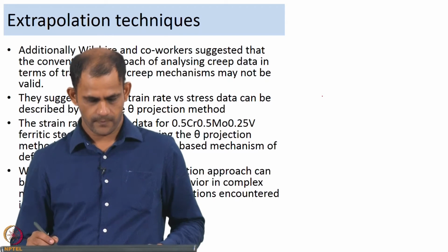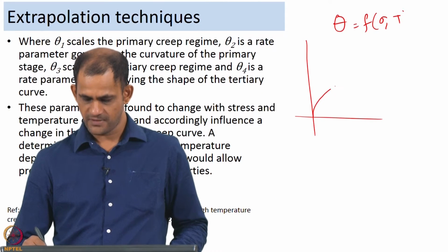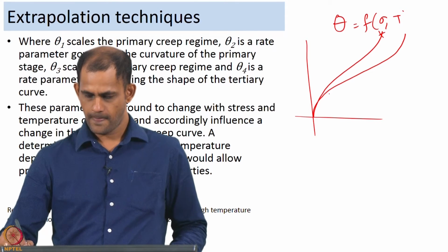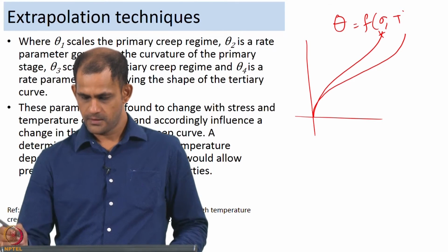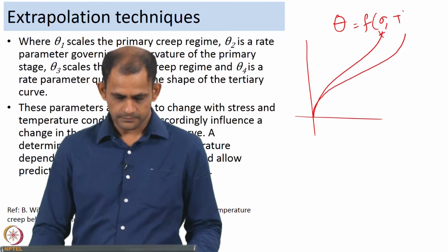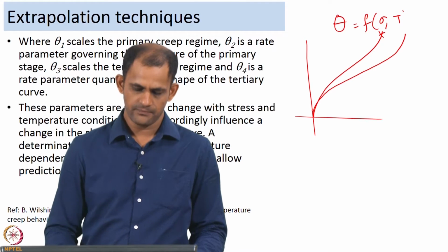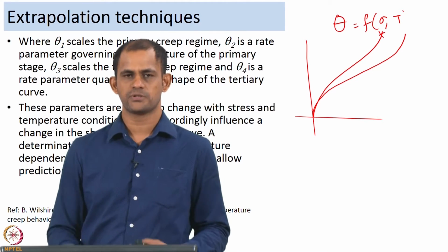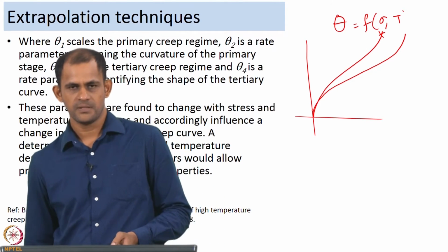So, the shape of the creep curve can change depending on the theta values corresponding to the stress and temperature. That is why they believe a determination of the stress and temperature dependence of the theta parameters can be used for prediction of the long term creep properties.